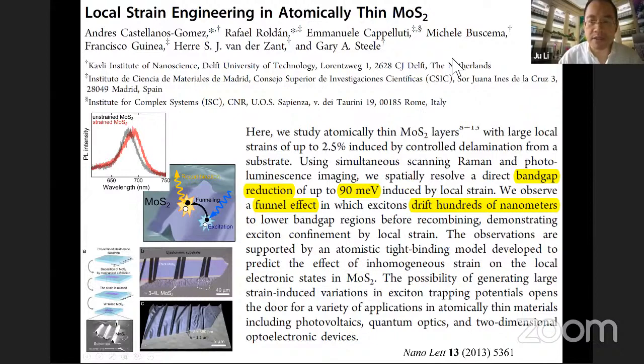But then there was this experiment from the Netherlands where they made this what we call a ripplocation. So you have basically a wrinkle of molybdenum sulfide, and at the valley here, the band gap is higher, and at the crest, the band gap is lower. And so they cited our paper and they demonstrated that indeed the exciton can drift hundreds of nanometers. In other words, they absorb the blue light here that excites this electron hole pair, which then moves to the peak of this ripplocation and recombines there and re-emits as a red-shifted photon. And that verifies this inhomogeneous strain engineering approach. Here, the strain is the bending curvature.